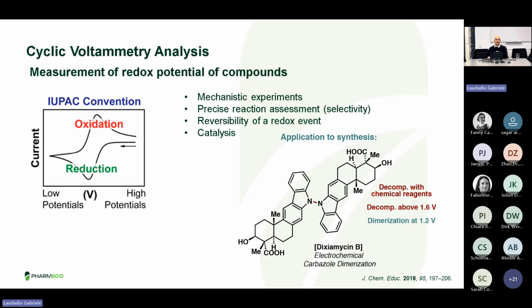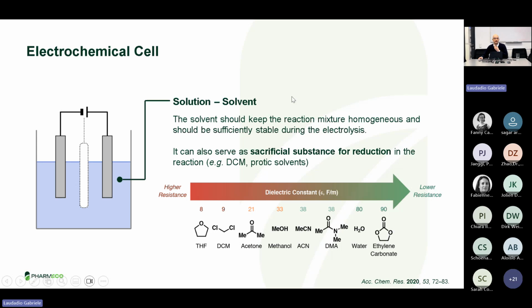Okay, so now we evaluated the electrodes. Let's look at what happens in the solution. The solution that we have to use obviously starts with the choice of the solvent. In organic electrosynthesis, we have to balance between solubility, so solvents that can solubilize our starting material, but also they need to be good at transferring and moving the ions. For that, we rely on a physical parameter called the dielectric constant. The higher this parameter, the lower the resistance of the cell. In particular, water, DMA, and acetonitrile are good solvents for electrochemistry, while, for example, THF and DCM are not really good.